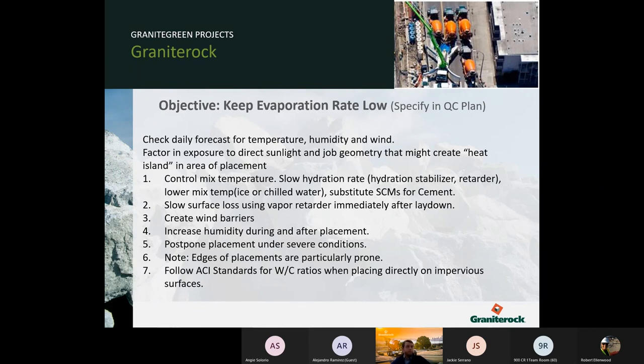To slow the hydration rate, you can use the set retarders that we talked about earlier. Slow the surface loss using vapor retarder immediately after placing the concrete. So think of the chemical curing compound that we talked about.